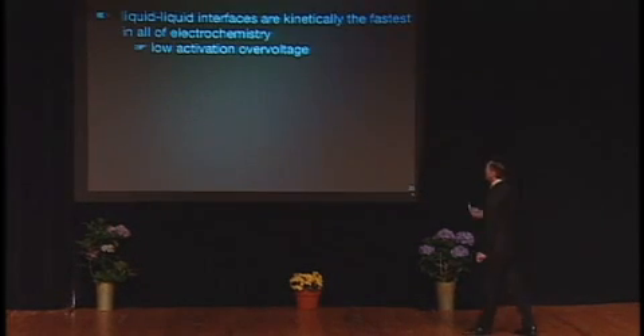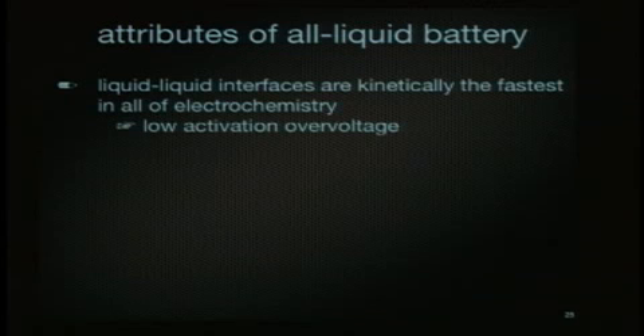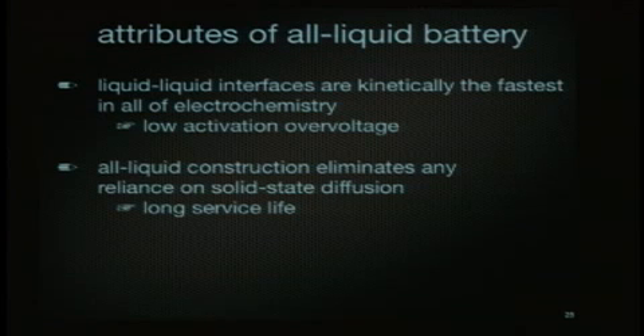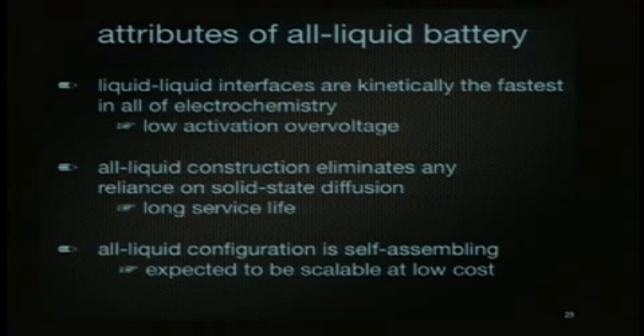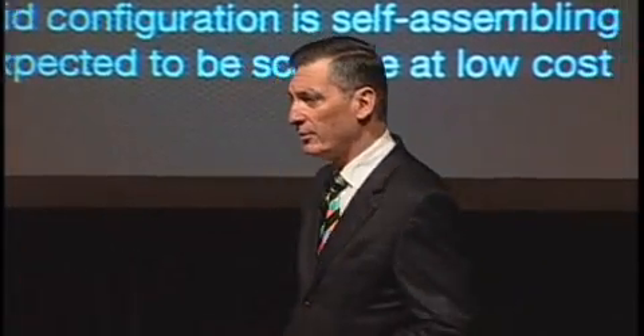All right. So what are the attributes of this? Very low activation overvoltage, so parasitic losses are low. No solid state diffusion, and that's what degrades your lithium-ion battery. We don't have any of that. And the all-liquid configuration is self-assembling. The low-density metal sits on top of the electrolyte, which sits on top of the high-density metal. They don't want to mix. It's like oil and water, and yet a third phase. No separators.